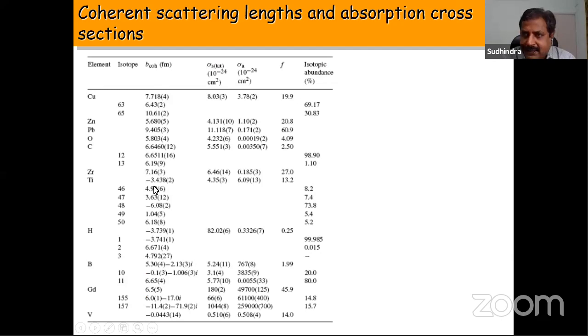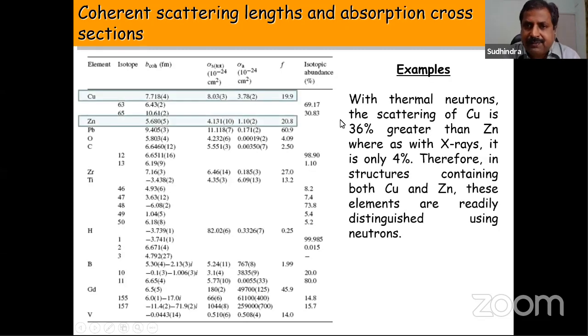Now, this is a comparison of scattering length for neutrons with respect to the X-ray form factors. Just to give you a brief example, you can see the scattering lengths for copper and zinc. If you look at the periodic table, they are one electron apart. But if you look at the X-ray form factor for copper and zinc, they're almost identical. The difference is about 4%. But in case of neutrons, the difference of scattering length between copper and zinc is about 36%, which means that neutrons will scatter both copper and zinc. It will scatter copper more than zinc. So if you do the structural analysis for a compound containing copper and zinc, you will be able to identify both copper and zinc. So you will be able to identify the occupancies, or the amount of copper and zinc present in your sample, more precisely than in case of X-rays.